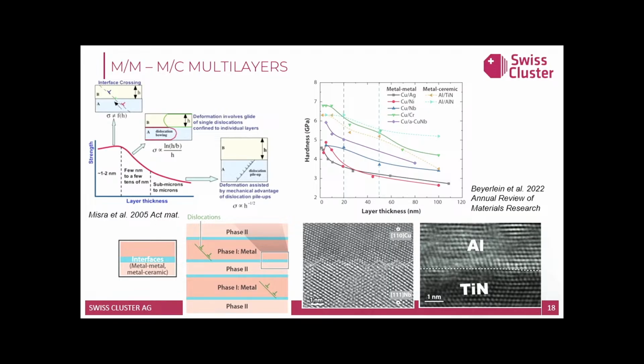So we always wanted to understand what was the effect of introducing ALD layers, whether it was because of having a grain size refinement or because of introducing an ALD layer, right? So we know that metal multilayers or metal-ceramic multilayers, mainly deposited by PVD, have an effect of increasing the hardness by decreasing the layer thickness of the multi-layer system.